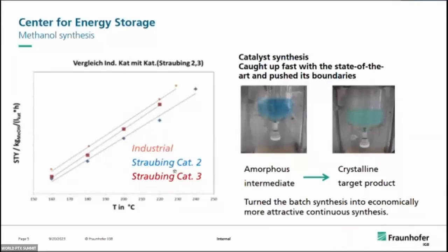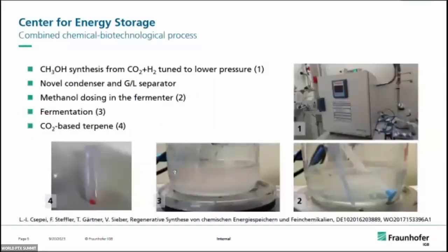We caught up very fast with the state of the art. As you can see, our third catalyst already approached 90% of the industrial catalyst. But more importantly, we pushed the boundaries of catalyst synthesis in that we converted the batch synthesis into continuous synthesis, which improves the yield per day by a factor of 2.5 to 3. That means you can almost triple the catalyst output with this synthesis, which, by the way, is the same. You don't have to add anything else. It's the same method, but we managed to optimize the production of the catalyst.